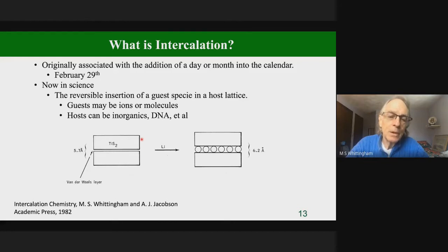So we have what we call blocks here: sulfur, titanium, sulfur. Then we have a van der Waals gap here, so very, very weak bonding. So this will interact with things like lithium, and lithium will insert in here, and it expands this lattice by about 10%, but does not change the lattice in any other way. So we break no real bonds, so we can take them in and take them out very easily. So let me now move on and show how this works in a battery.